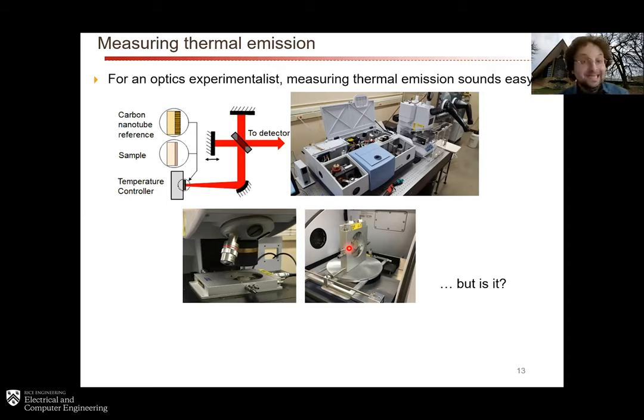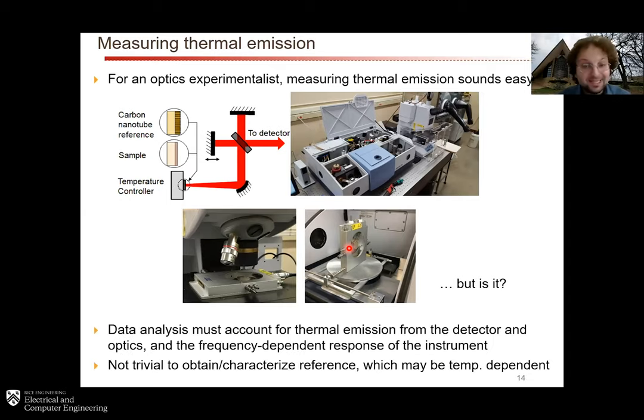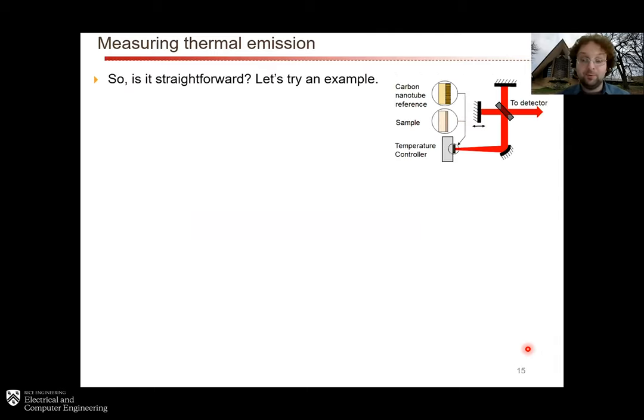The question is, is it actually straightforward? And the answer is not exactly, because the data analysis of these kinds of measurements has to account for thermal emission from not just the sample, but also from the detector, from the optics. You have to take into account the frequency-dependent response of the instrument. It's not necessarily trivial to obtain and characterize a good reference. Often references are temperature-dependent or have sharp spectral features that need to be accounted for. So this is overall not as simple as it sounds. It requires a lot of care.